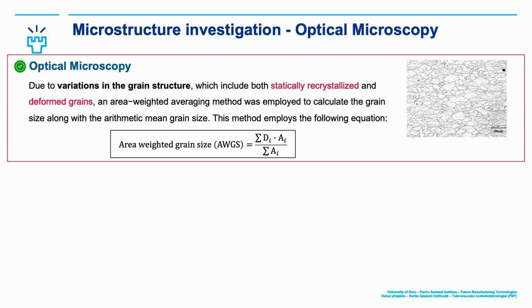Moving forward with the optical microscopy, according to our investigation, we found a mix between the statically recrystallized and deformed grains. So to have an accurate estimation of the grain size, we compared both methods: the arithmetic mean and the area weighted grain size. We used some image processing incorporated with machine learning to accurately measure the grain size, so we could have accurate data for each single grain, and then accordingly apply the area weighted grain size.